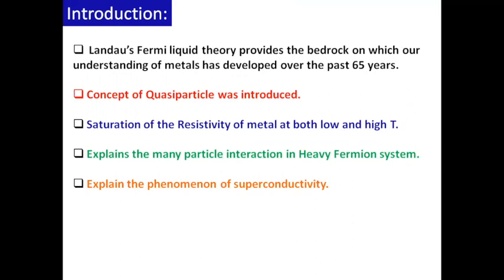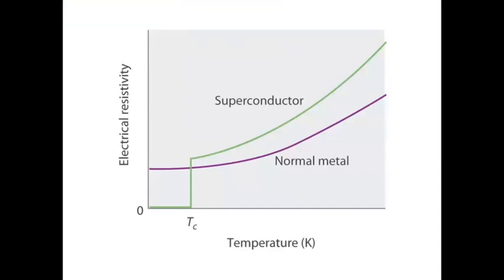So that is the concept of quasi-particles. Why am I telling this in a more subtle way? Because we'll see how all of these things have been violated in the material which people have named strange. Then there is the saturation of resistivity. You have all seen the resistivity of a metal. Suppose I have a normal metal like copper or silver. This violet plot is nothing but the resistivity of a metal. You can see the non-zero resistivity at zero temperature, which is familiar from Matthiessen's rule and is associated with defects and impurities, followed by electron scattering.